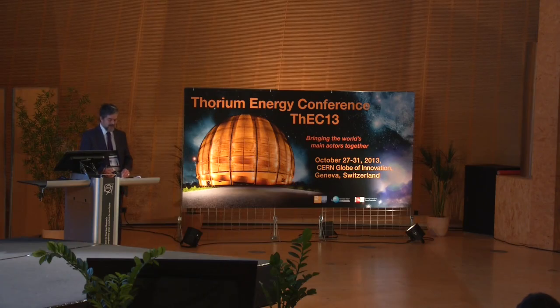Alternative alloys are under investigation, but this adds to the development cost and to the lead time. The molten salt reactor is definitely not an off-the-shelf option. The molten salt reactor maximum operating temperature is set by corrosion rates and lifetime targets, which does not make it a very hard temperature limit. Transients and brief excursions can go above that and still have an acceptable rate of corrosion. But nearly all the operating time should be below that temperature limit.